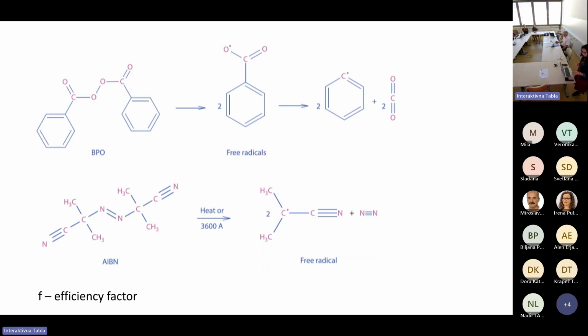Here is a typical equation for the situation of benzoyl peroxide and azobisisobutyronitrile. And if we look at benzoyl peroxide, at the first stage, benzoyl peroxide breaks and two free radicals, benzoyl radicals, are formed, but these benzoyl radicals can break down further to create phenyl radicals. And about initiators, it should also be pointed out that because of recombination and because of side reactions, not all radicals that are formed are involved in the polymerization process.